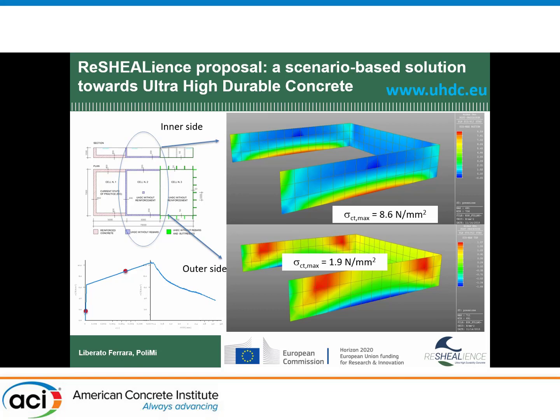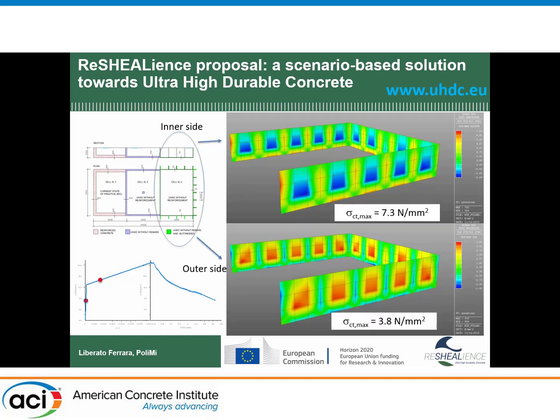So we try to even improve the structural concept. We say, why don't we think of something partially precast, just precast some square slabs and use some buttresses cast in place, and we install the slab and put the buttresses so that each slab will work like a square slab clamped on 3 sides and free on the other one, instead of being a big cantilever slab. So in this case, the stress has reduced, and you can see here we are at about 7 MPa of principal tensile stress on one side. But the most important thing is that the strain in the service condition is just 0.2%.